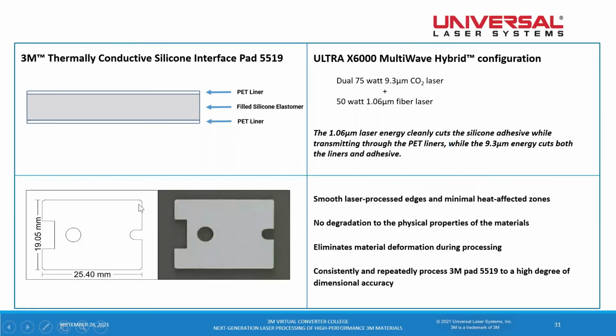And then our last example is the 3M thermally conductive silicone interface pad 5519. If you remember, we used this to demonstrate the capability and benefit of our MultiWave hybrid technology. What's interesting about this is it also has the same PET top and bottom liners, but the middle layer is a filled silicone elastomer. And the CO2 wavelength is not absorbed at all within this layer. So by combining a high power CO2 along with a 50-watt fiber laser, we're able to cleanly cut through this material and provide the same kind of quality edge and minimal heat effects as the other examples.